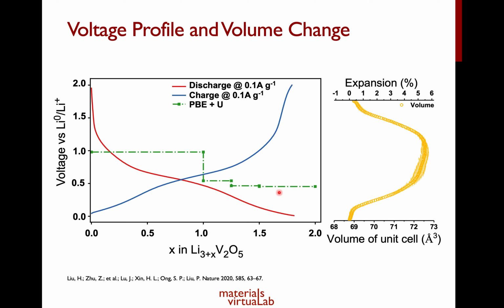And this green dashed line essentially shows you the average voltage that we compute using the PBE plus U functional. All that I want to say here is that the average voltages are in fairly good agreement with what we actually get from these experimental voltage curves that were measured by Ping Liu. Now, during the lithiation and the delithiation process, we also found that the volume expansion for this anode is actually fairly small. It's only up to about 5% or so.